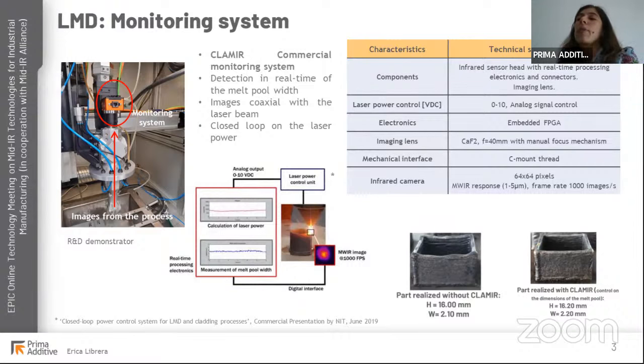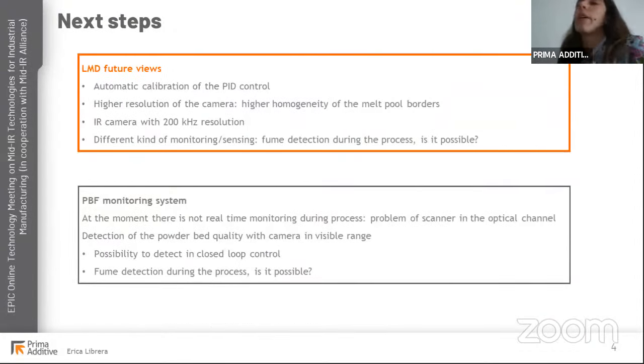With the help of CLAMIR, we are able to correct this effect, to modulate the laser power in order to keep the process constant and stable. And at the end, we obtain a flat geometry. But we are studying a lot around the monitoring system because we want to integrate more and also to understand more the information coming from the process. In particular, we are looking for a higher resolution camera in order to collect more information and to be able to deposit more precise geometries with smaller features.